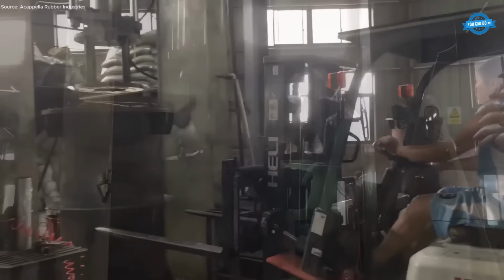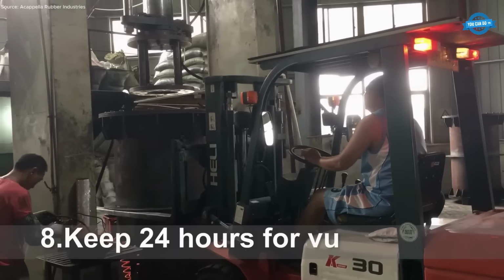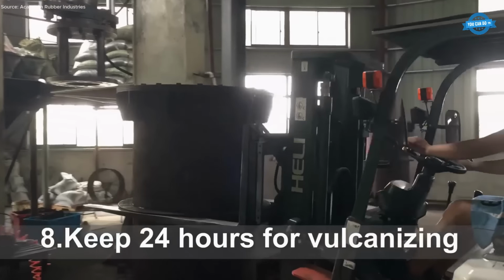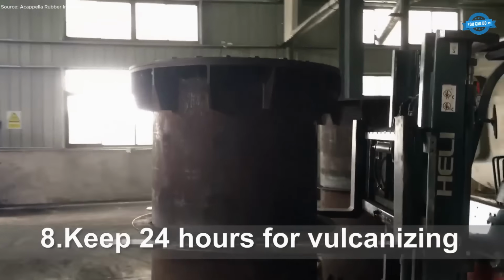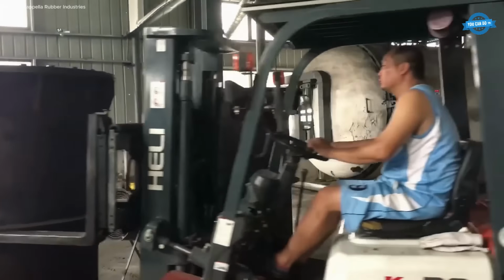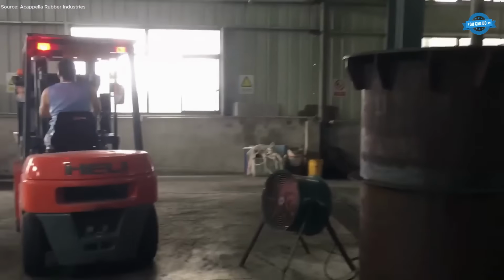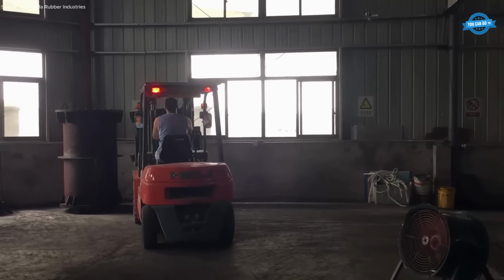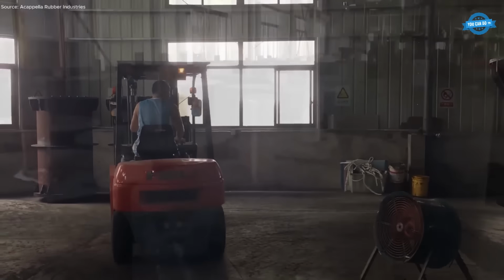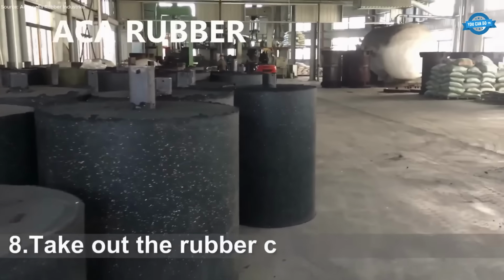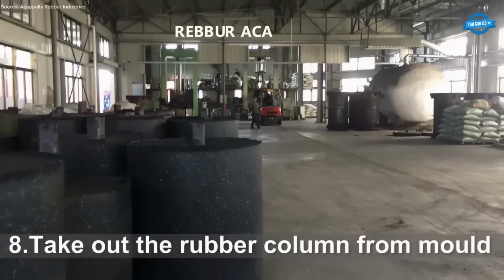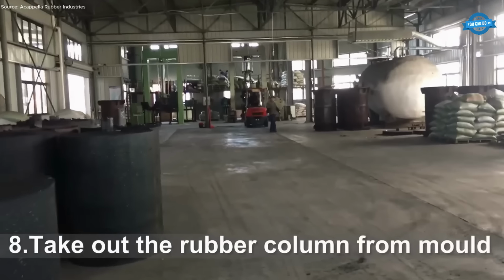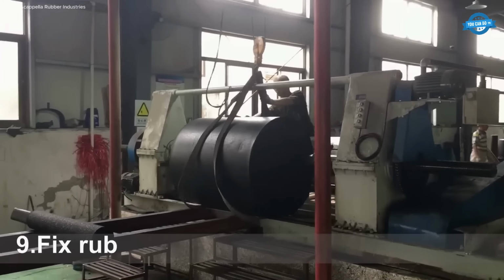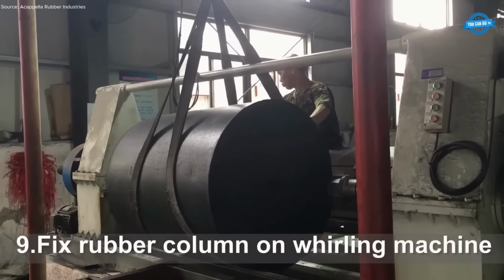The mixed crumbs are then transferred into a mold, a process that takes approximately 15 minutes to completely fill the mold. Once filled, the mold is subjected to a hydraulic press applying 31.5 megapascals of pressure. This high-pressure pressing compacts the crumb mixture, ensuring a dense and cohesive structure. The mold is then fixed in place and left for 24 hours to undergo vulcanization, a chemical process that strengthens the rubber by forming cross-links, enhancing its durability and resilience.